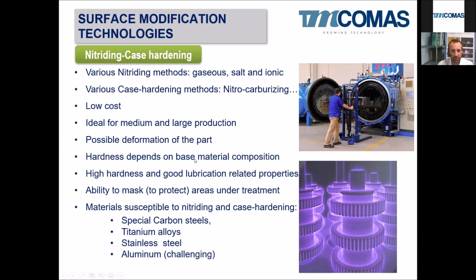The hardness depends on the base material. Yes, that's true. There are special steels for nitriding. There are special steels for case hardening. So not all the steels will reach 1,000 Vickers, and not all the steels will be suitable for nitriding, for example. So just check with your supplier which steels can be optimal for that. High hardness and good lubrication properties. Yes, with these surface treatments, the surface is very hard and it has some lubrication properties. So it's very much used for gears, for example, keeping the core of the steel in a tough state and just making a hard surface to avoid wear of the gears.